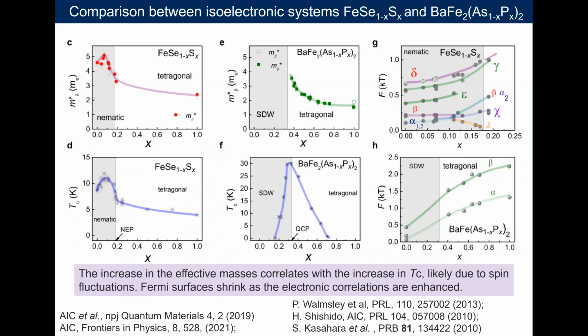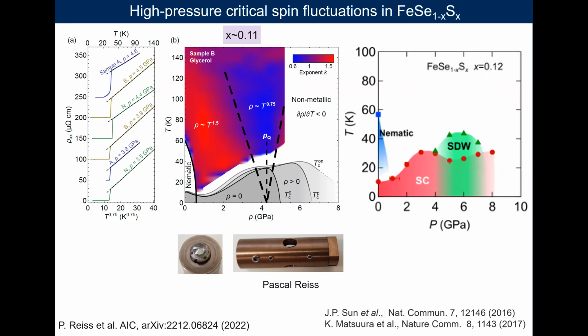And if we summarize the two systems here, we see that actually Tc increases slightly inside the nematic phase. This is where the effective mass also increases. So potentially we have the spin fluctuations, but they are active only inside the nematic phase, and those are the dominant fluctuations which affect superconductivity, as compared with the barium 122 system.